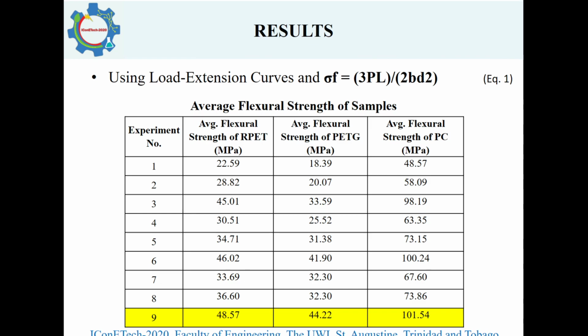The table shows the average results of 5 repetitions for 9 sample sets of each material. So what is to note here is the strength of the polycarbonate, or PC, was the highest, while the RPET and the PETG were similar in strength. Finally, the sample set 9 had the highest flexural strength.